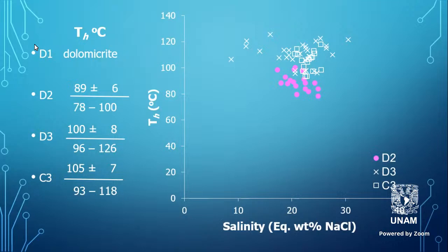Of course, the dolomicrite is micritic. We cannot measure fluid inclusions in a crystal of around 4 microns, even 30 microns, because the fluid inclusion in that crystal will be how many microns? 4 microns? 1 micron, 2 microns? You cannot measure that.